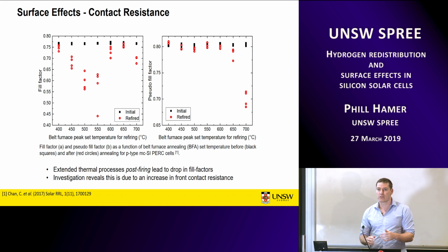There are some great thermal processes both Catherine and Chen have worked out and come up with that can completely eliminate your degradation in your bulk silicon, that can make it like it was not there at all. The problem is, as you can see here, your fill factor can undergo a catastrophic decrease. So while you prevent maybe 5 to 10 percent of degradation in performance due to lifetime changes, you can lose something like 20% in terms of your fill factor, and that's not really coming back.